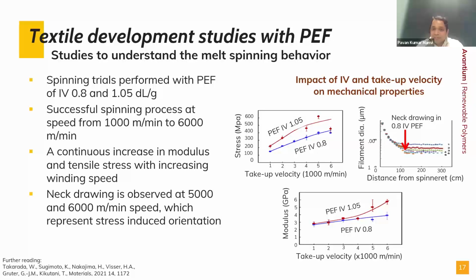In the first curve, you can see that if we use one IV but different take-up velocities, the stress continuously increases. And with the higher IV, we can even get a higher stress value. Stress means the tenacity value, and this is also valid for the modulus. One very important phenomenon we have seen while measuring the filament diameter with the distance from the spin pack is that there are some specific distances where we can see the neck forming behavior, and neck forming behavior is directly related to the strain induced crystallization. There are some specific speeds, mainly above 4000, and depending on the IV, it can be 4000 and 5000. At these speeds, we can get the neck forming and the strain induced crystallization in the filaments.